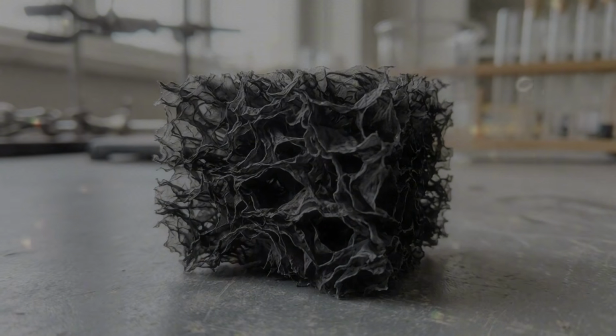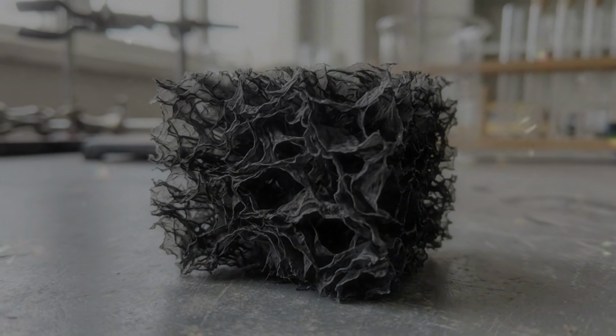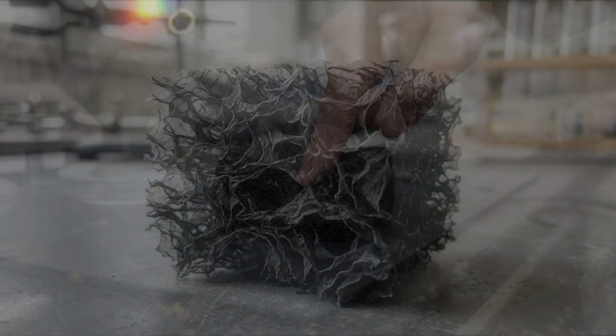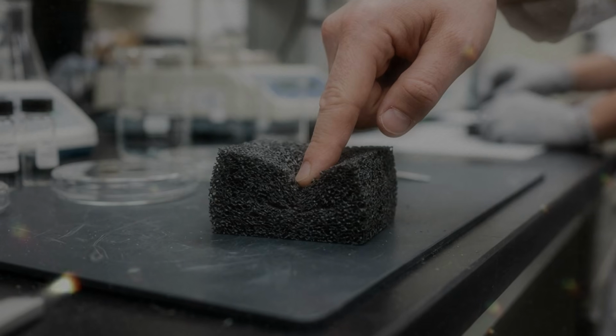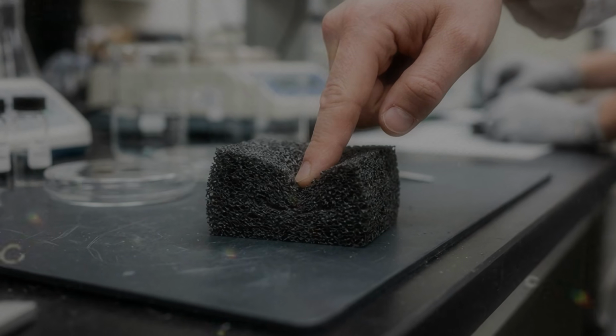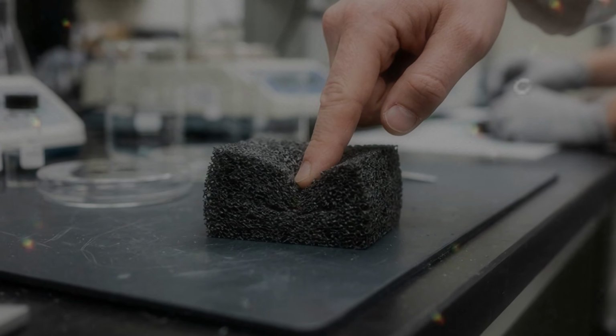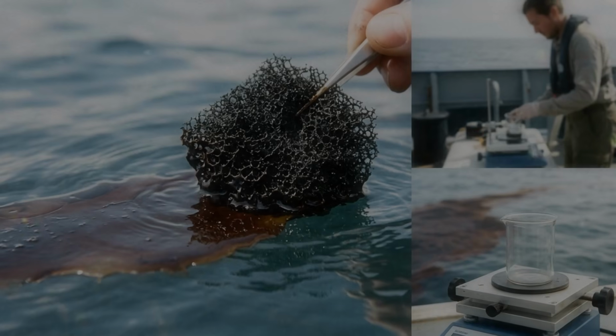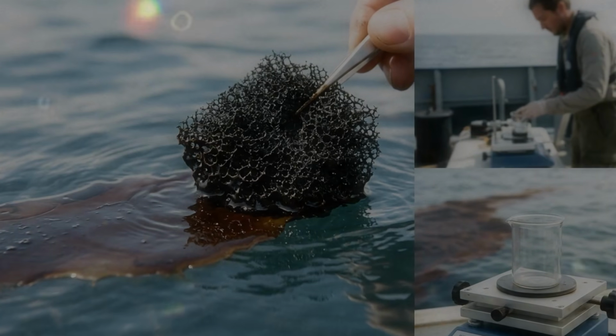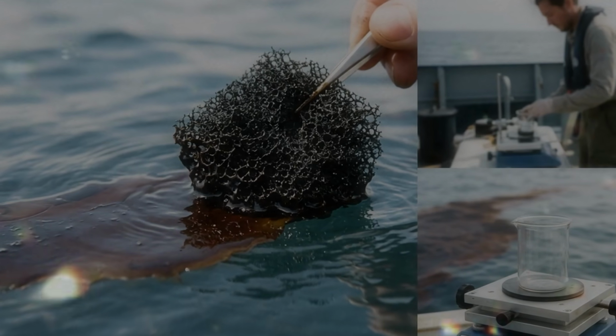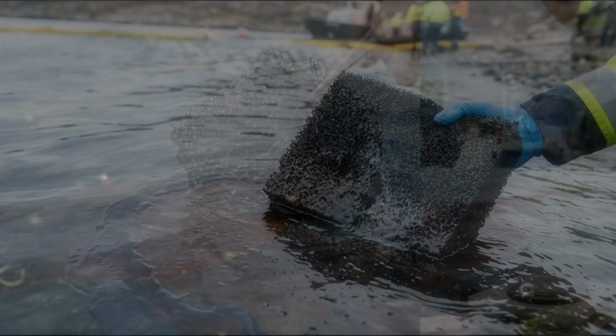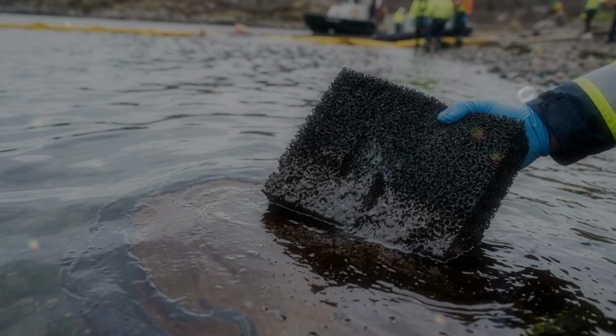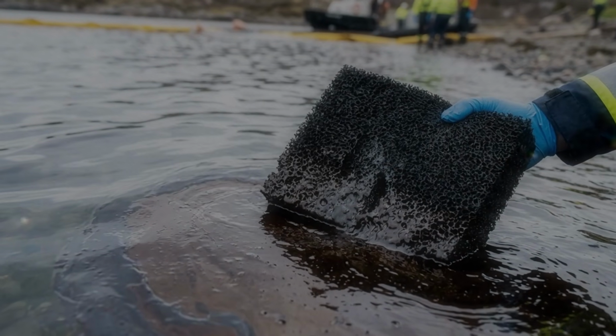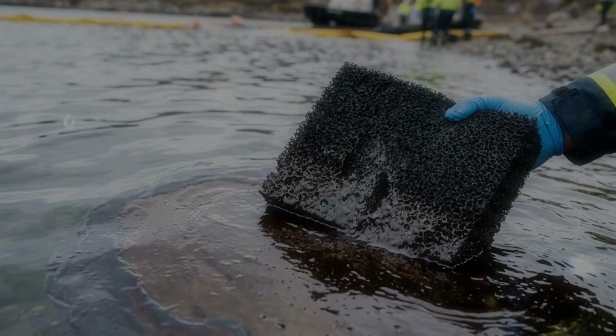Improving one can weaken another. Adding carbon improves conductivity but increases density. Adding polymer improves strength but may reduce heat resistance. Closing pores protects the interior but blocks liquids and sound. A practical design accepts these trade-offs. It does not chase the highest result in every test. It chooses a combination that survives real conditions.